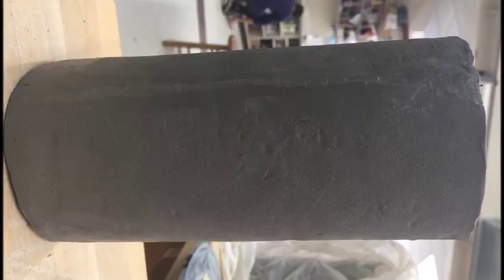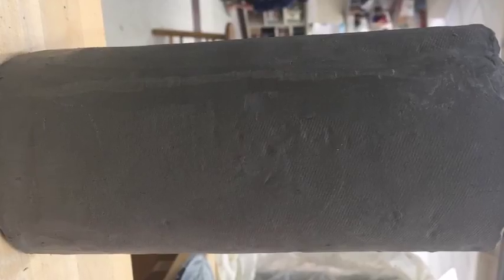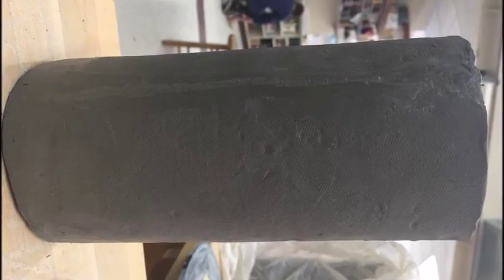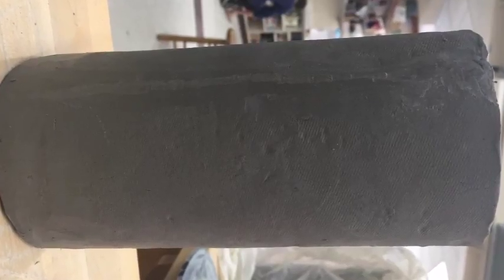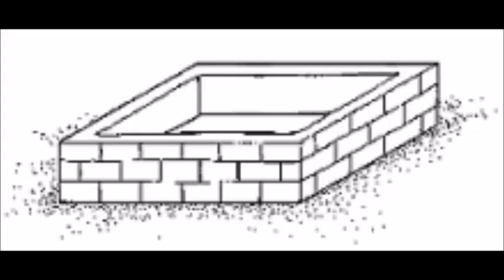During the excavation, a pavement corer was used to remove an 18-inch cylinder of glass near the center of the slab. It took an entire day to drill it out. After grinding and polishing, the piece was removed. A scientist showed that the glass was homogeneous from the top down, until it came within a few inches of the bottom on the tank floor, where there were partially reacted ingredients that had not completely melted. At the very bottom was some of the original batch, which looks today like coffee grounds. Coming from above, the heat had not penetrated all the way through.